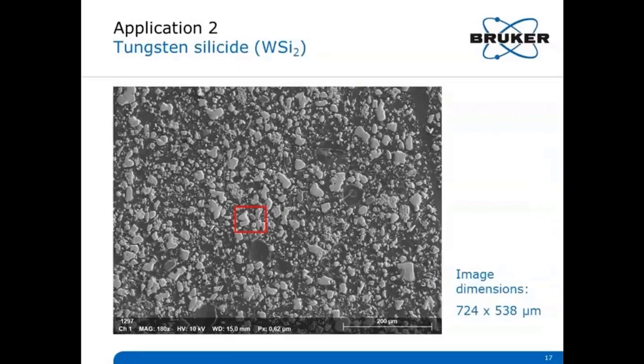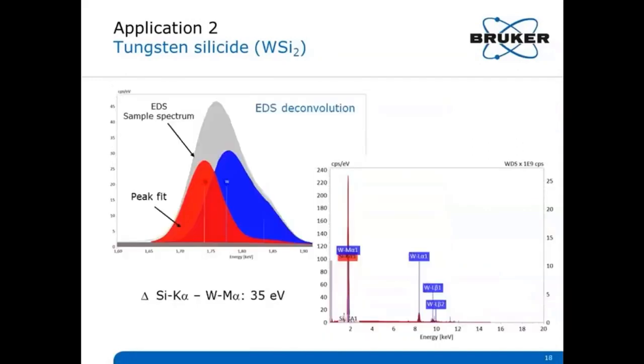The second sample is tungsten silicide. The electrically conductive ceramic material tungsten silicide is used in microelectronics such as microchips. The present sample, which we analyzed, is granular with particles of about 10 micrometers in diameter. The red square here, more or less in the center of the image, indicates the mapping area, which we see in one of the next slides. At first here we see some point analysis.